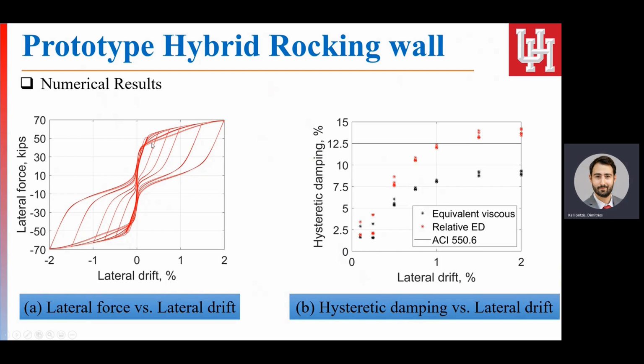So you see that here the response is relatively stable. Also, the wall experiences pretty good recentering. The residual drifts are below 0.4%. So the recentering capability of the wall is pretty good, and also the hysteretic damping that we achieve through the heat treatment meets the requirement of ACI 550.6 that requires a relative energy dissipation of 12.5%. So this is the horizontal black line that is shown here, and the red dots are the relative energy dissipation that were achieved by this wall, and it essentially corresponds to the energy that is enclosed within the loops shown in the lateral force versus lateral drift graph.